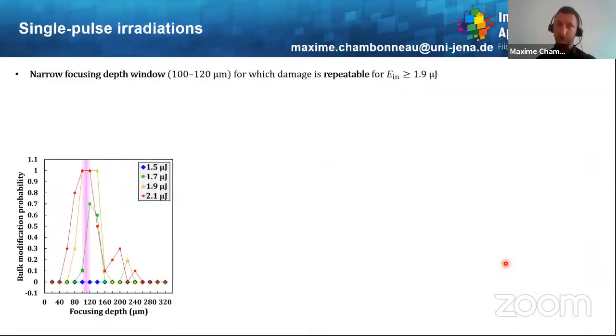Okay, so what about the experiments? So we have carried out single pulse irradiations, and here are the results in terms of modification or damage probability in the bulk of silicon as a function of the focusing depth. One can see that it is absolutely non-monotonic, and one can reach 100% damage probability inside the bulk of silicon, so repeatable modifications at focusing depth around 100 to 120 micron. And of course, you need some sufficient input pulse energy, so higher than 1.9 microjoule.